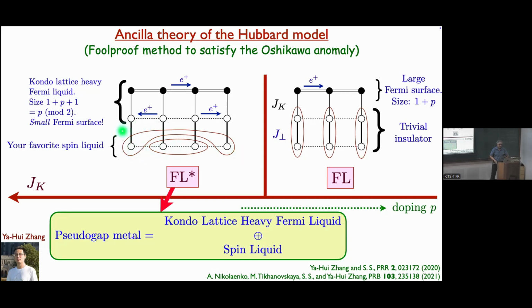And that's related to the fact that the area of this Fermi surface here is exactly p. It's not some other value between p and 1 plus p. It's really quantized by the anomaly of the spin liquid. And the spin liquid is very rigid. It remains that at the insulator. So that was another difficulty in many of the early works. You started with a spin liquid and you doped it, and you started modifying the spin liquid in ways that are not really allowed. You have to keep it very rigid, and the ancilla does that automatically.